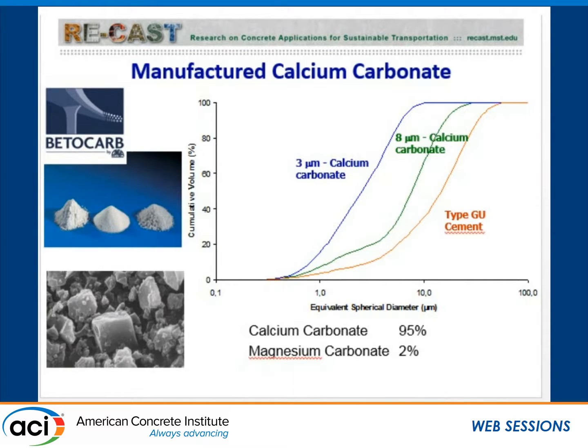We were looking at the potential use of limestone filler as an addition or replacement in SCC mixtures. And like Eric mentioned, the motivation there is to increase the powder content. But we did not want to use a lot of powder like what they do in Belgium or in Germany or some of the European countries, where they go 300 kg of cement and 300 kg of limestone filler, and that's a very, very high powder mix, no VMAs, but very viscous. We wanted to adapt it more to what we use in North America.